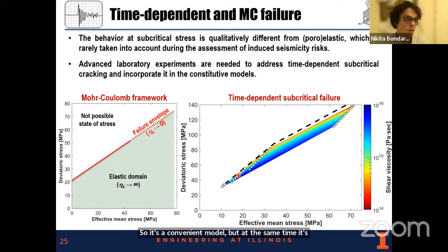By performing the test I mentioned, we see that this time-dependent response and associated viscosity of the rock changes significantly as we approach the failure envelope. This means we can nucleate macroscopic failure even if we are not at the failure envelope, but below that, by exposing the material for a long time period.